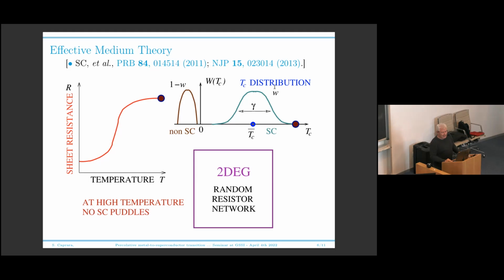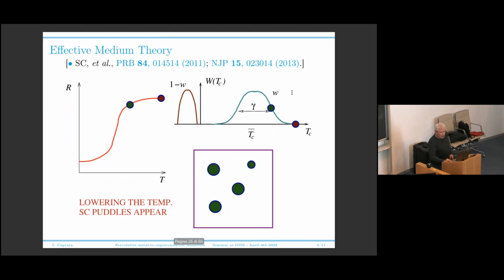So I assign a total weight W to the superconducting component and the total weight 1 - W to the metallic component. And then I start from very high temperature. My temperature is here, this temperature is larger than all the critical temperatures of all the superconductors. And then you have a metallic state. Your resistivity is the resistivity of a metallic state. Then you start lowering the temperature. For instance, now you are here.